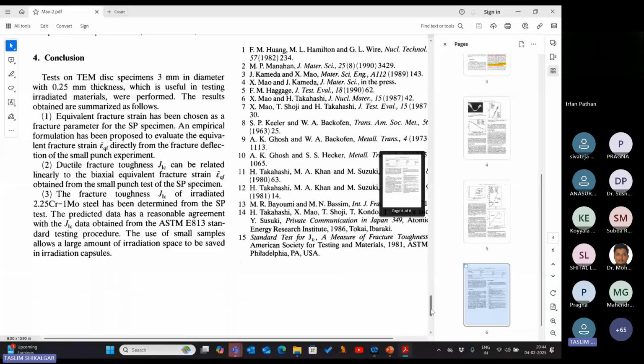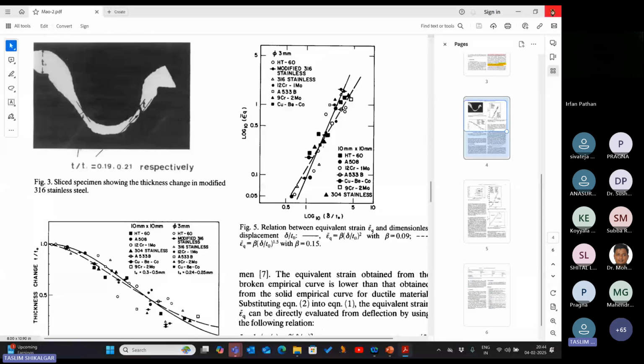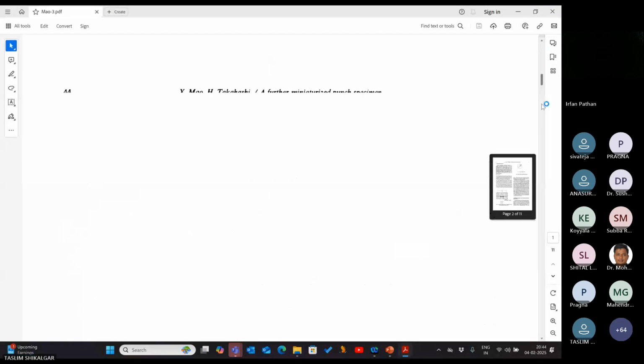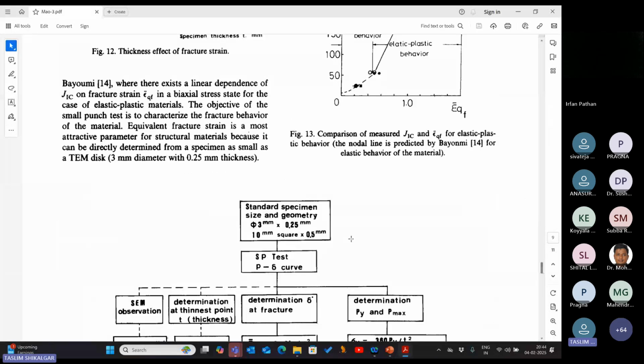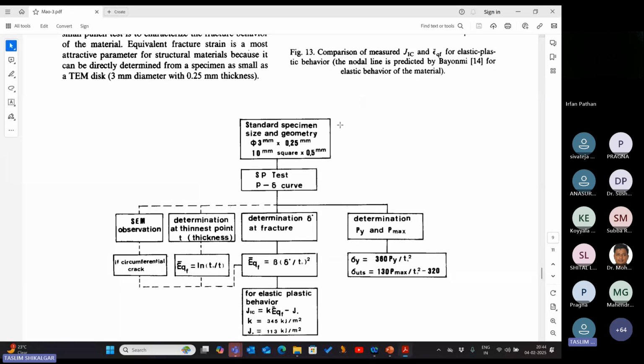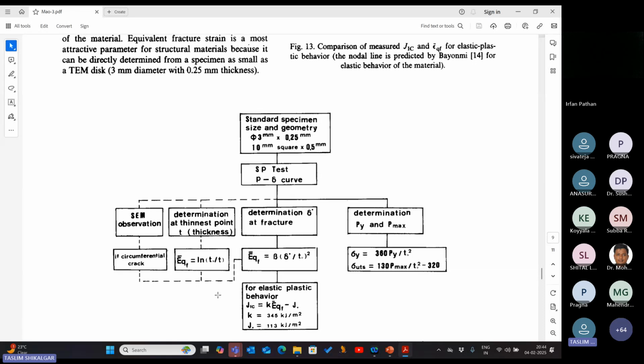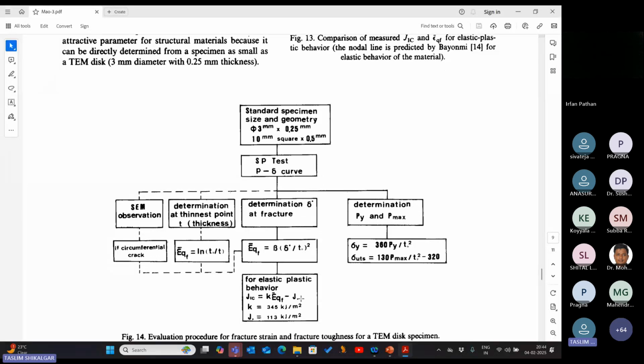Here, in one paper, he showed how we can use this approach to get the fracture property. He calculated the equivalent fracture strain as ln of initial thickness divided by final thickness, and plotted it as a function of the J integral. He calculated K and C like a linear equation, and with the help of this he tested many materials. So with this specimen you can easily get J1C. This is an old approach, but a very interesting approach he developed 30 years before.